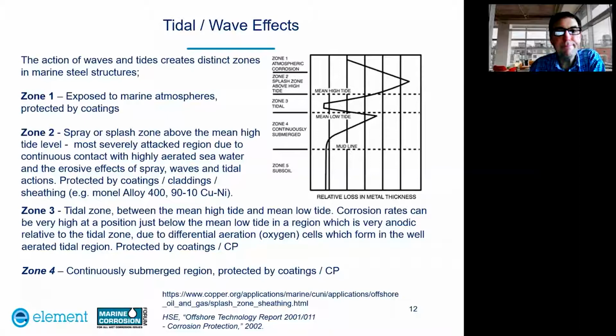Keeping on the topic of oxygen, the action of waves and tides creates distinct zones in marine steel structures. This sketch shows the relative corrosion, or loss in metal thickness, of a carbon steel going through this tidal zone from the atmosphere, down through the splash zone, through the tidal zone, and then into the submerged region. These regions can be split into several zones.